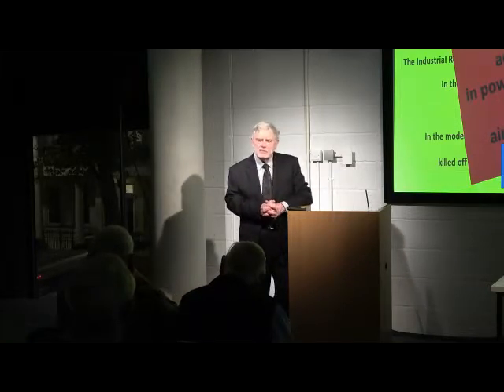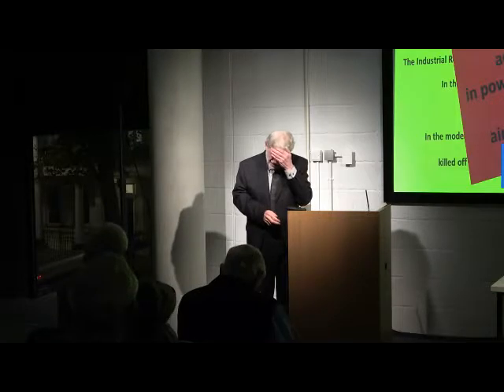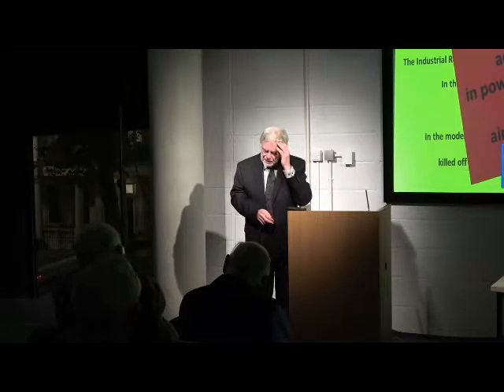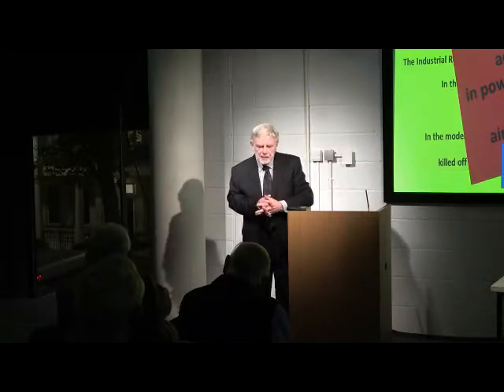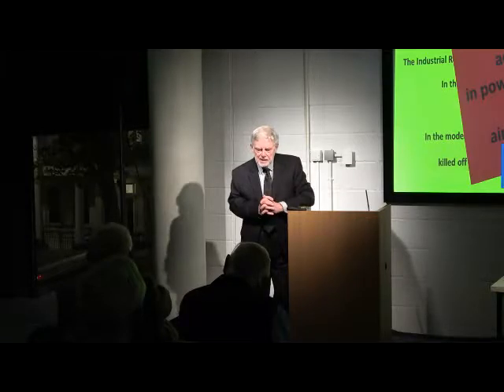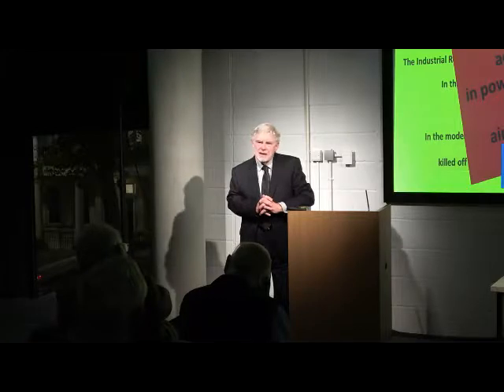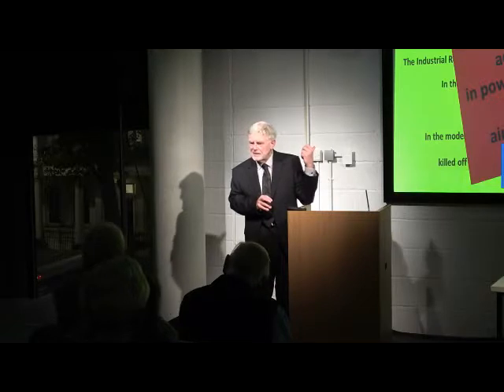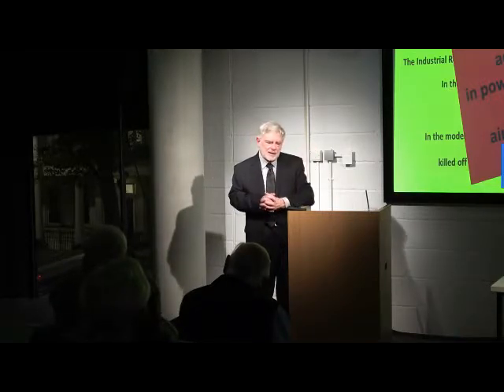Well, that's really quite interesting, and it goes back to a problem that we had in British Gas in the 1960s. Fortunately, we started supplying natural gas rather than town's gas. But it was becoming apparent that carbon monoxide could cause stress corrosion. And it is quite possible that in these stoves you've got carbon monoxide coming through, and that is part of the problem.